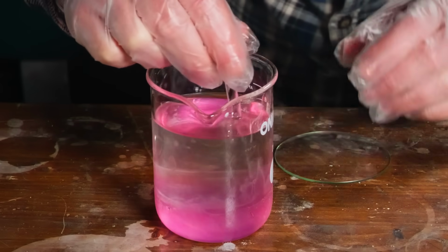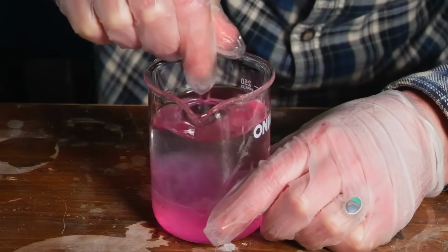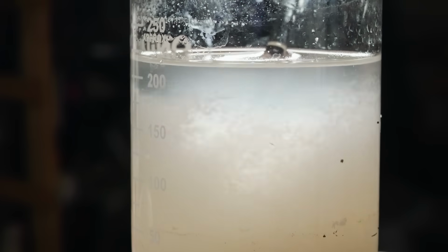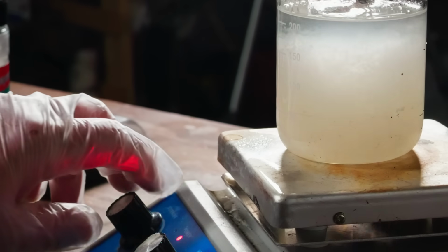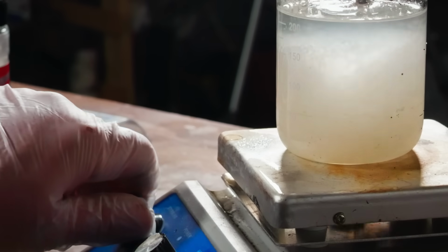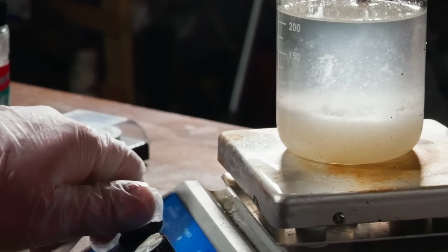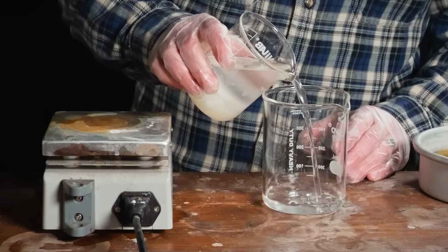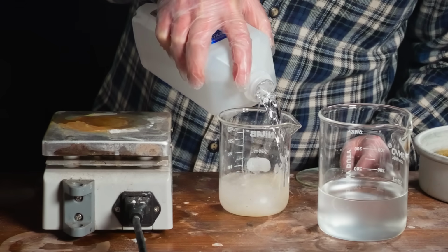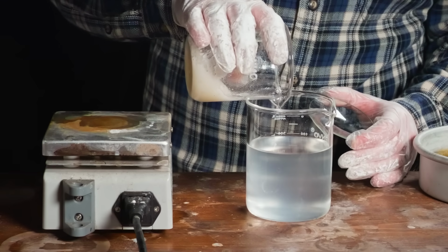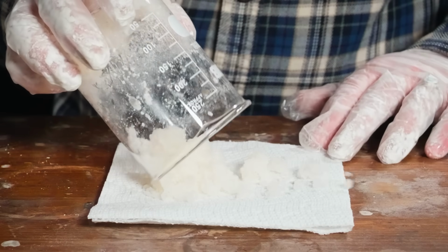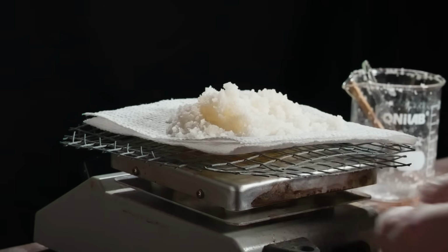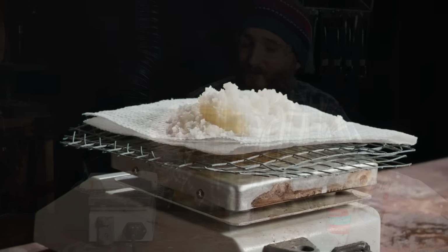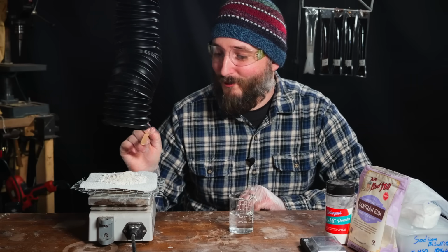Well, it didn't precipitate at the alcohol boundary, but after stirring, the CMC does seem to have solidified and is now floating around as solid chunks. If I stop the stirring, we should be able to pour the liquid off the top. And I'll refill it a few times with fresh alcohol to hopefully remove whatever's left of the water and other things contaminating our product. Well, we have some sort of result here.